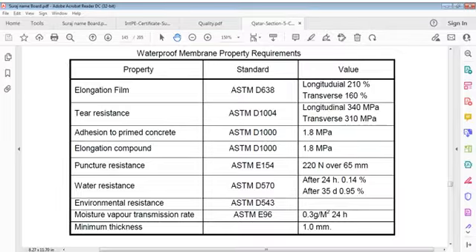We are talking of waterproof membrane property requirements. So elongation 210%, 160%. Tear resistance 340 MPa, 310 MPa. One direction, other direction. Adhesion to primed concrete, ASTM D1000, 1.8 MPa. So elongation compound and adhesion to primed concrete are both the same.